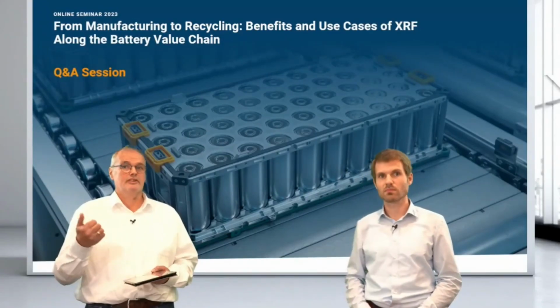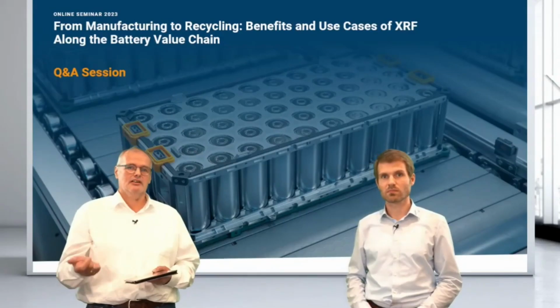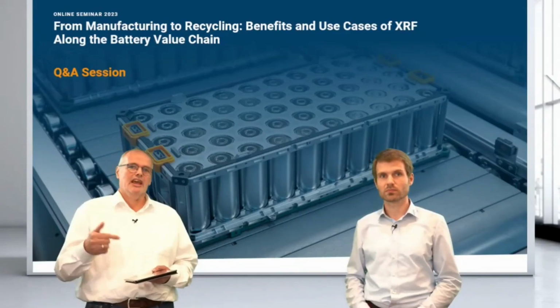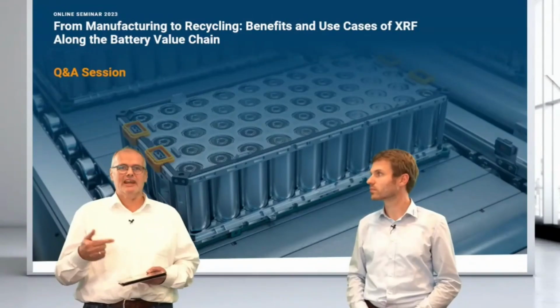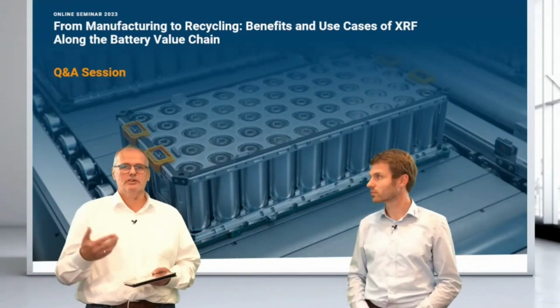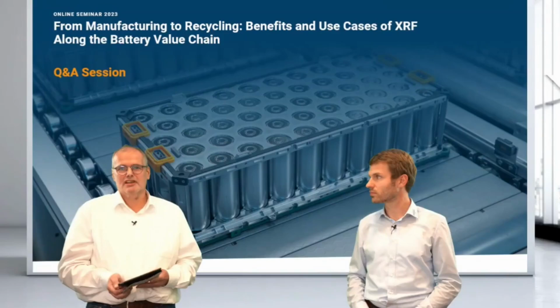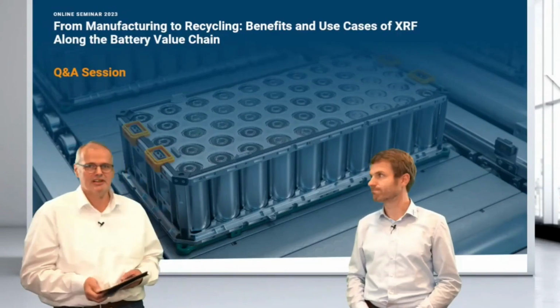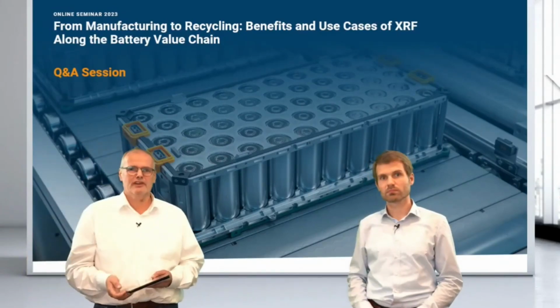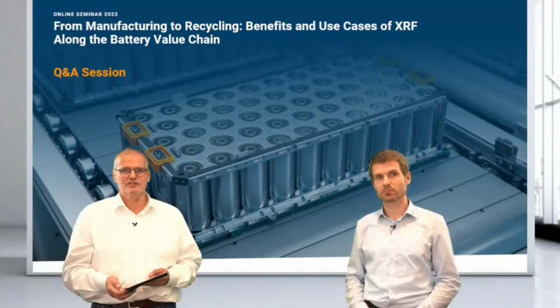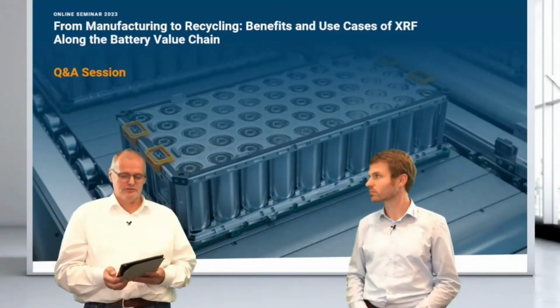So with the theoretical and fundamental parameters, and knowing the rest to 100 and the Compton ratio, we can almost always get very accurately to 100%, and also correct for effects like changing carbon values or changing aluminium values.